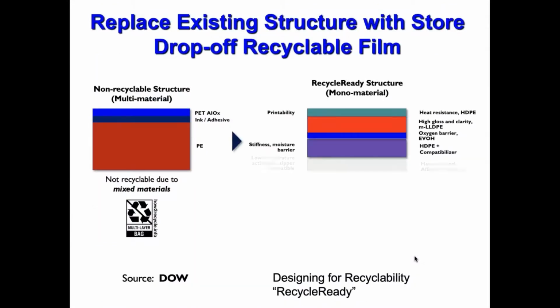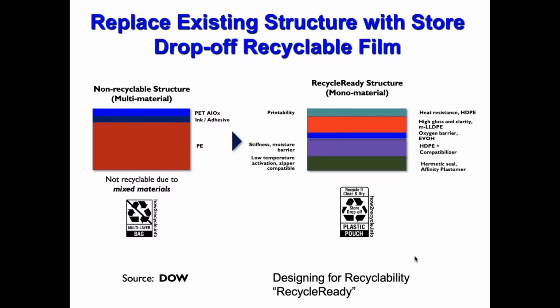So this is to give you an idea of what Dow developed, replacing the non-recyclable structure on the left there, which is multi-material with PET and PE and also a barrier layer of some kind. Replacing that with a recycle-ready structure, a monomaterial structure on the right, which is mostly polyethylene with different types of polyethylenes for different functions like heat resistance and the sealing layer on the bottom there. These can incorporate an oxygen barrier such as EVOH. And if that's done to make them, again, recyclable, a compatibilizer is incorporated as part of one of the HDPE layers.